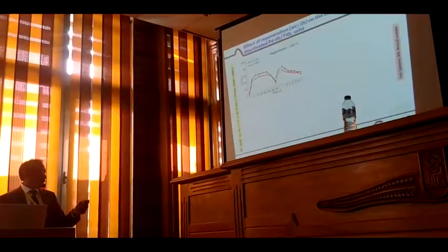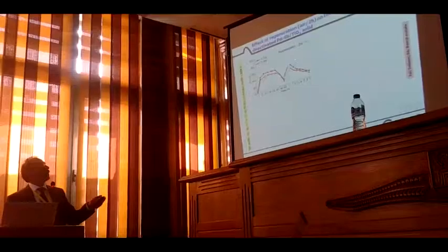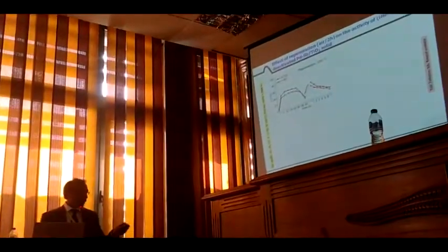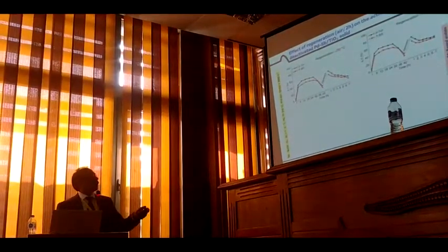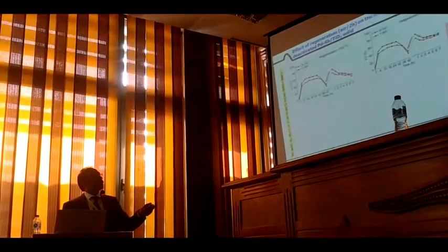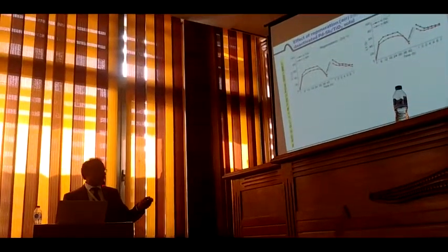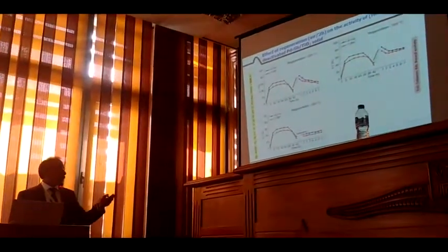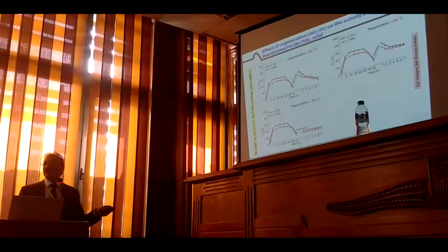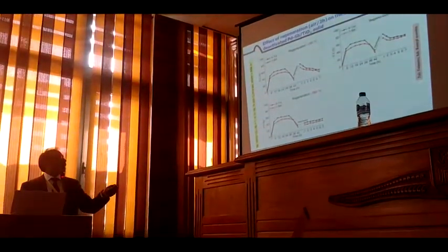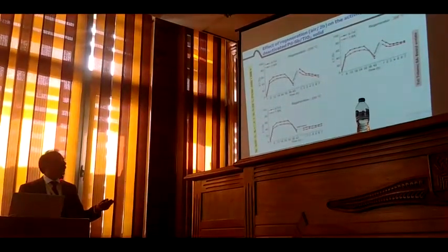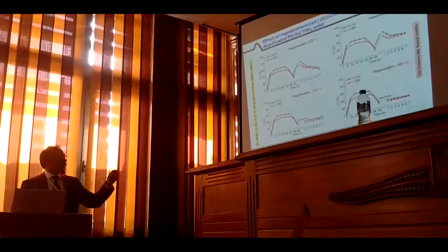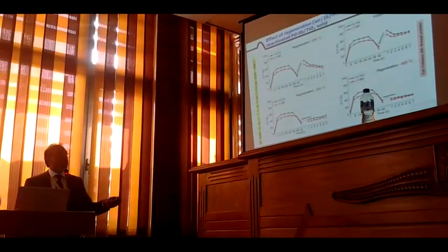So we tried to regenerate the sample at 250. We are able to regenerate, but the regenerated catalyst undergoes faster, rapid deactivation. This prompted us to go a little higher, to 300, which is somewhat better. And then we thought, okay, maybe if you go to 350, it might be much better than this. Quite surprisingly, we are not able to regenerate at 350. At 300 you can regenerate, but at 350 you can't. So something different chemistry is going on. Then we also went beyond 350. We went to 400, same situation.